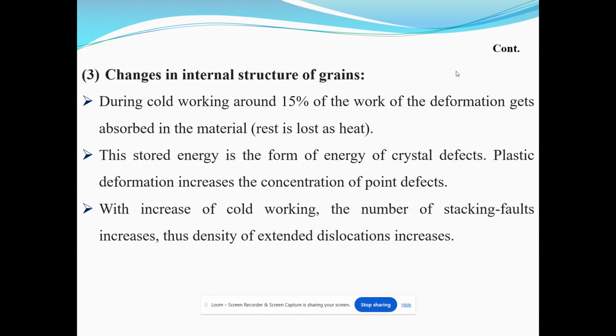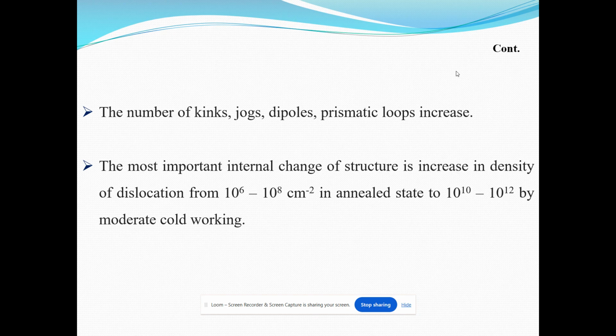Changes in the internal structure of the grains. During cold working, around 15% of the work of deformation gets absorbed in the material. The rest is lost as heat. The stored energy is in the form of energy of the crystal defects. Plastic deformation increases the concentration of point defects. With increasing cold working, the number of stacking faults increases, thus the density of dislocations increases. Because of dislocation interaction, the number of kinks, jogs, dipoles, and prismatic loops is increasing.